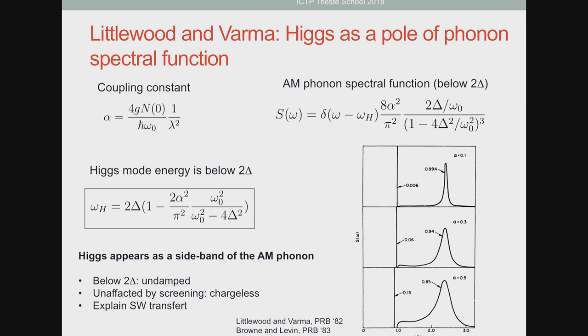So they actually derived an energy for these coupled excitations, and it's always sitting below 2 delta. So the fact that it's below 2 delta is good. It means it's going to be less damped than the conventional Higgs mode. It's unaffected by screening. This is also an important aspect, because the Higgs mode does not carry any charge, so Coulomb screening is not going to affect it. And this naturally explains the spectral weight transfer between the two.